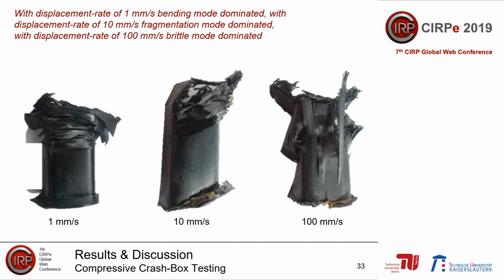So we see that with the lowest displacement rate of 1 millimeter per second, we have a deformation mode of folding and bending which dominates. When we increase the displacement rate to 10 millimeters per second, we have a deformation behavior of fragmentation of material. As we increase the deformation rate further, we have a deformation mode of brittle failure, which is characterized by fragmentation and expulsion of material.